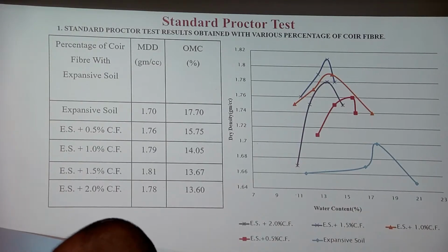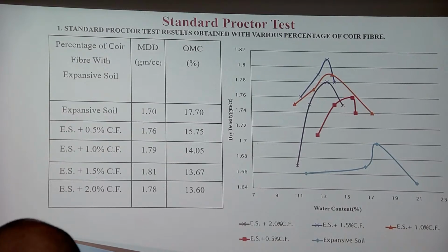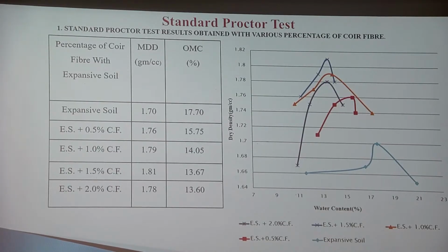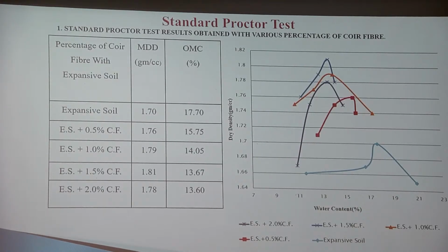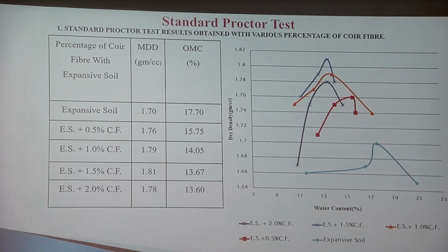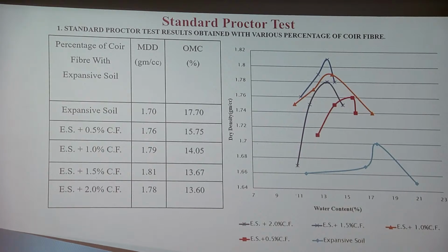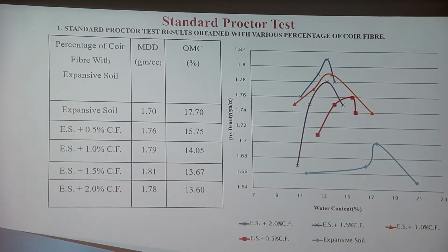Sir, in this test, at first we find the OMC and MDD of soil, which is 1.70 gram per cc at 17.70 water content. Further, we mix soil with different percentages of coir fiber. Then I found that the maximum dry density increases and OMC decreases at 1.5% content of coir fiber. After again increasing the coir fiber, the MDD starts to decrease.